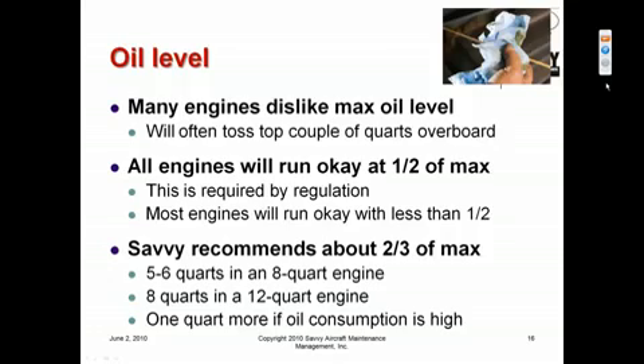in fact, most of these engines will run on a lot less oil than that, quite happily, particularly Lycomings. Many Lycomings will maintain good oil pressure and good temperature with oil down as low as 3 quarts or less, even if they have a big 10 or 12 quart sump. So there's no particular advantage of filling these engines full of oil. And if you do fill them full of oil, they typically will chuck the first couple of quarts overboard. Some engines do that more than others.